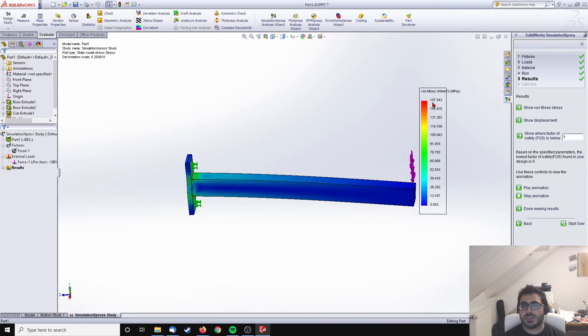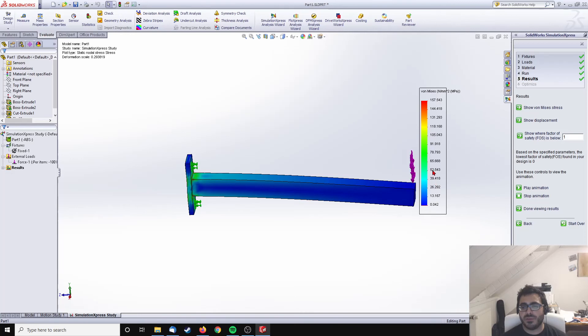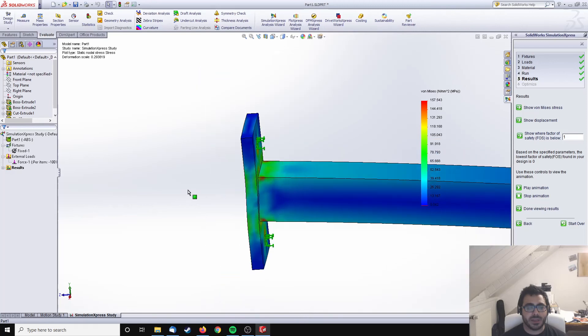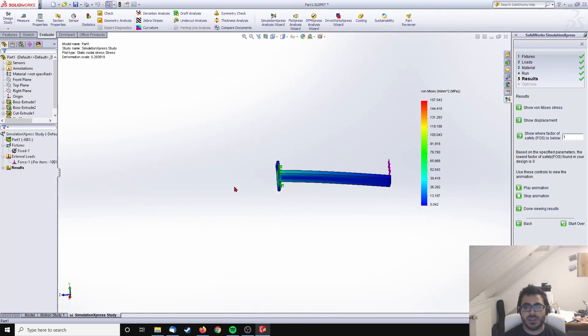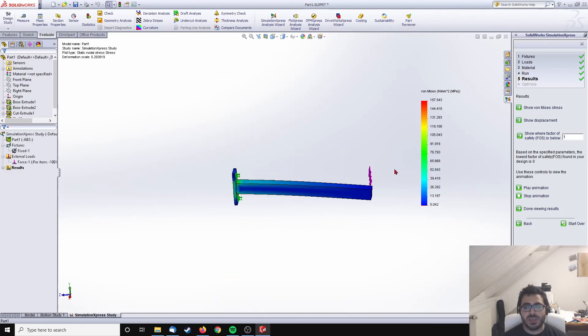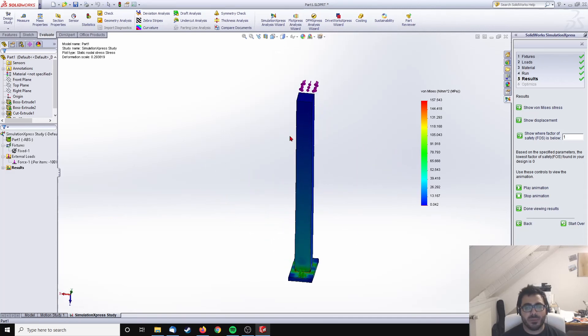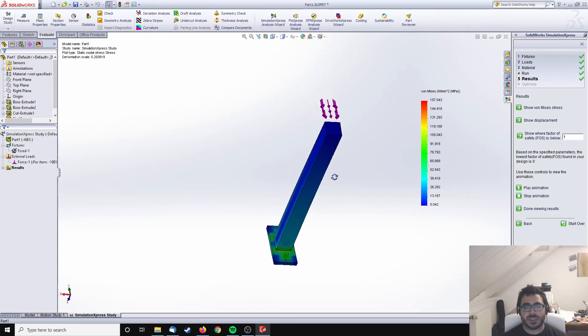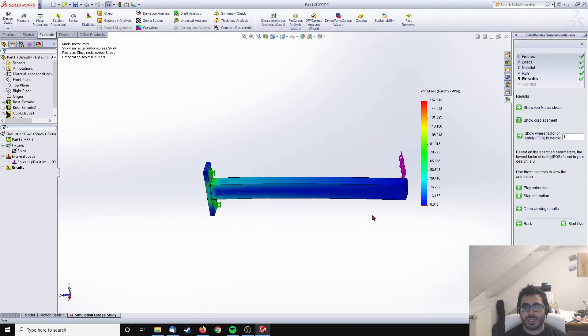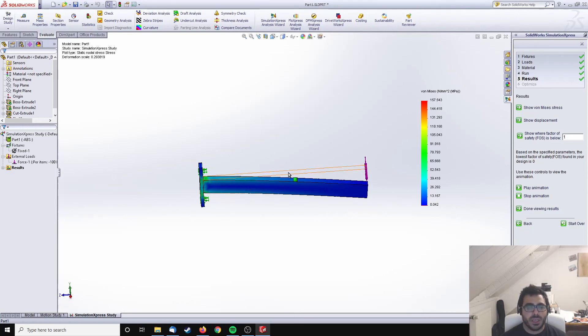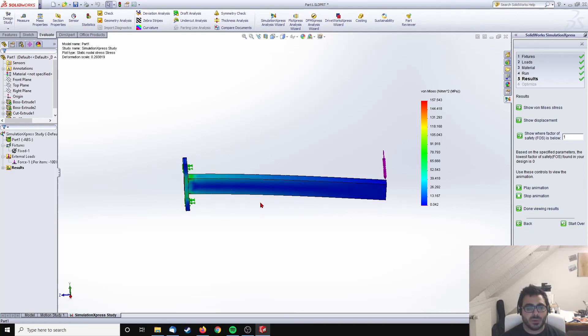You can see these values of stresses, they're very high. ABS fails at near 50 MPa, so around almost turning to green. Everything green here has already failed. This beam will not be able to carry 100 newtons, 10 kilos of weight, because it has a lot of porosity in it. If you print this going upward, you'll have layers and these layers will delaminate and detach. So this is totally a failed design if the load is going to be 100 newtons and there will be a lot of work to do.